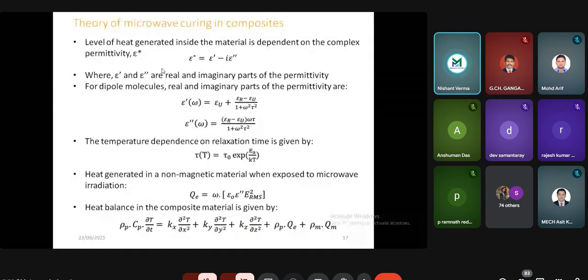Basically, generally two factors are responsible for microwave heating. One is the dielectric constant factor, second is the dielectric loss factor. So generally the complex permittivity depends upon both factors, and the temperature dependent relaxation is an exponential function of the electromagnetic waves. After that, the heat is produced. Heat is again a function of dielectric constant and dielectric loss factor, as well as the produced electric field. So in the case of non-magnetic material, the magnetic component of the field is cancelled out, and only the electric field is responsible for microwave heating.